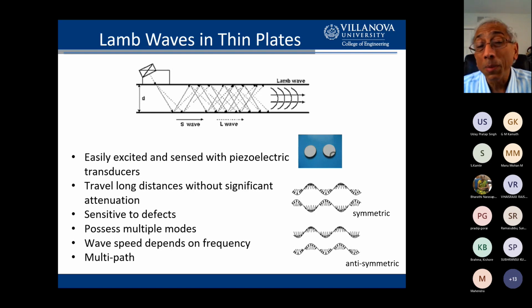Another issue with these waves is that the speed depends on frequency, and transducers such as these, when they initiate a wave, we try to initiate them at a specific frequency, but invariably you get a range of frequencies that are triggered, and each frequency travels at a different speed. And so consequently you might send out a nice tight wave initially, but because of the multiple frequencies in the wave, it spreads out, and suddenly what was a nice tight wave or a pulse is now a very wide pulse as it hits a defect and then arrives at your receiving transducer. And consequently, again, your information is spread out over a long period of time and overlaps with other incoming waves, thereby muddling the picture even more.